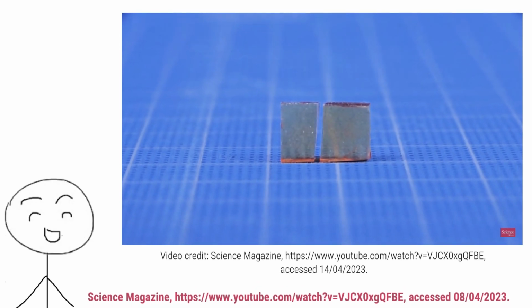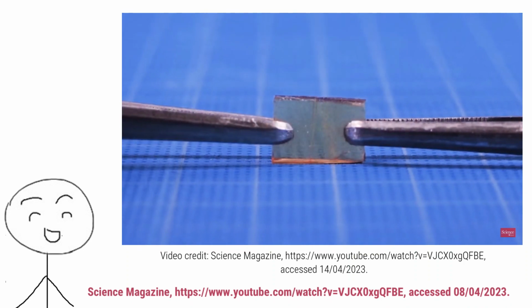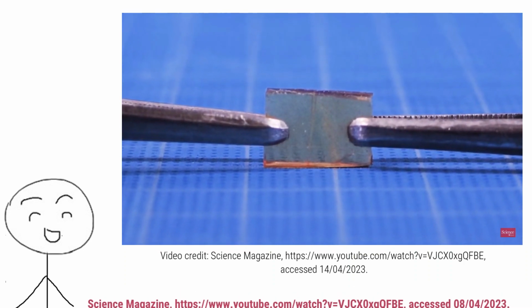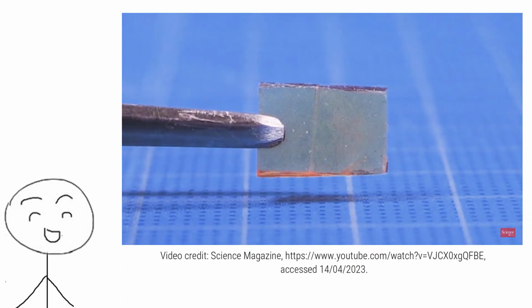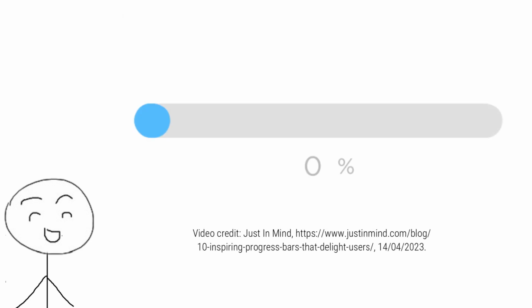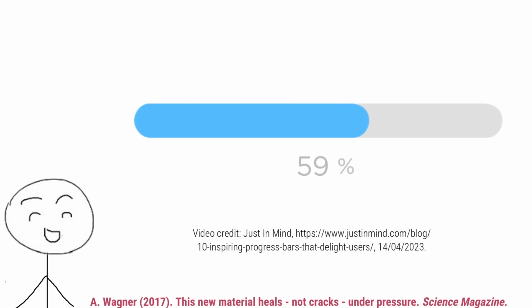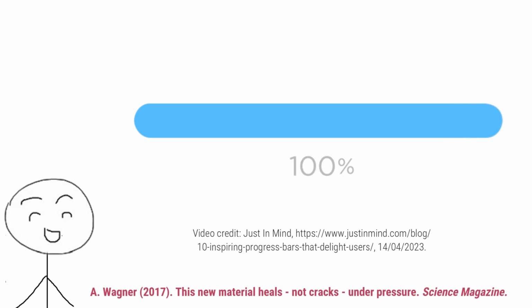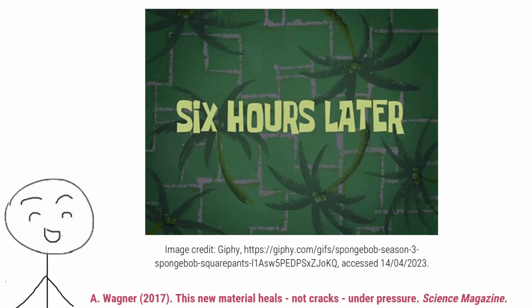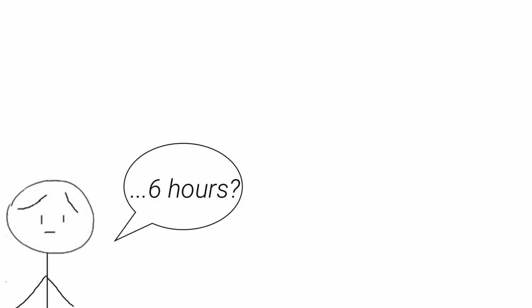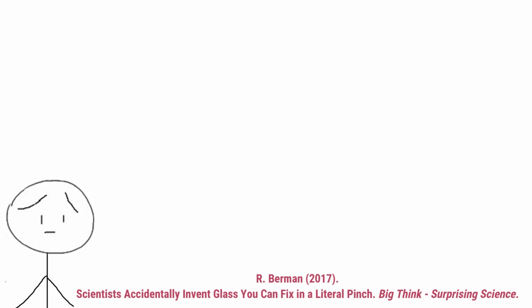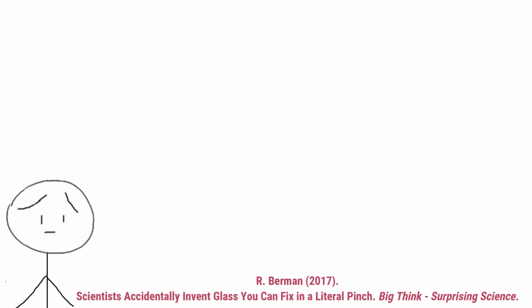TUEG3 is semi-transparent, which makes it ideal for shining light through for a phone display. And it only takes 30 seconds for a 2x2 cm square to repair itself. What's more, recovery back to 100% strength takes a quarter of the time as PVDF HFP does. TUEG3 needs just 6 hours of compression. Yeah, but that's good. And if you want, you can just put a small weight on the break while you're sleeping. It can hold up to 300 grams in weight.